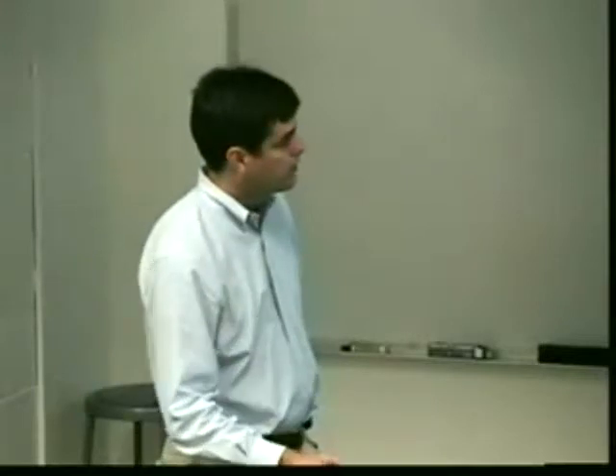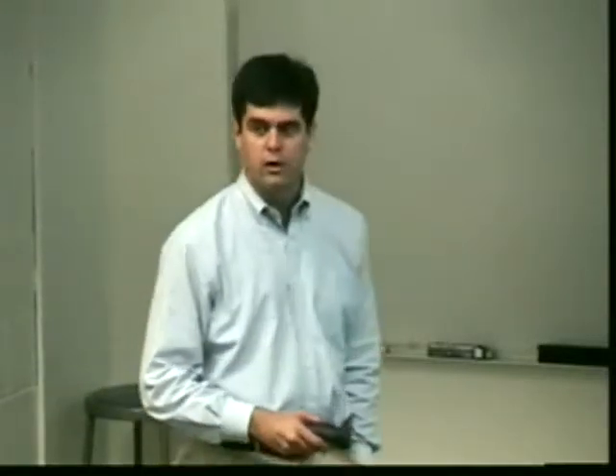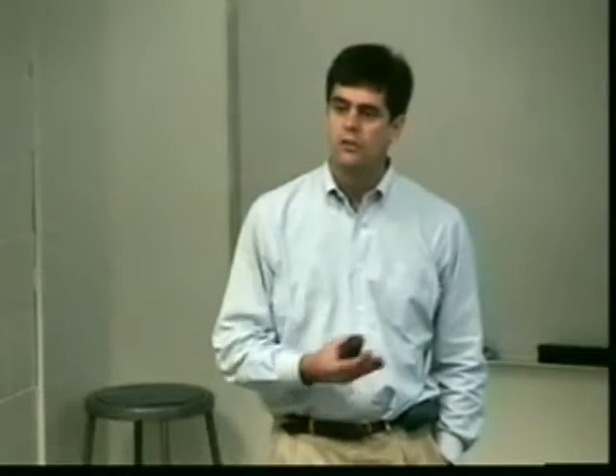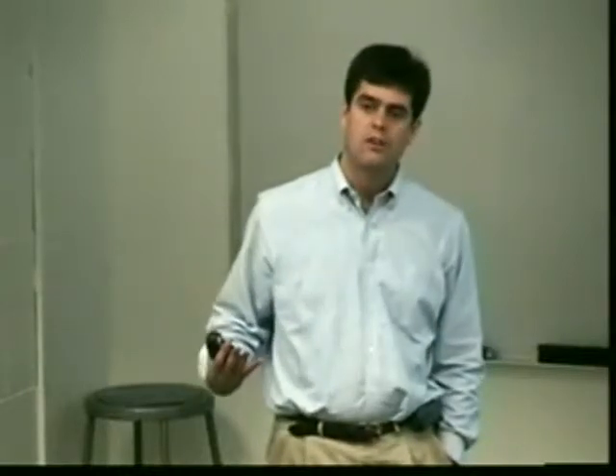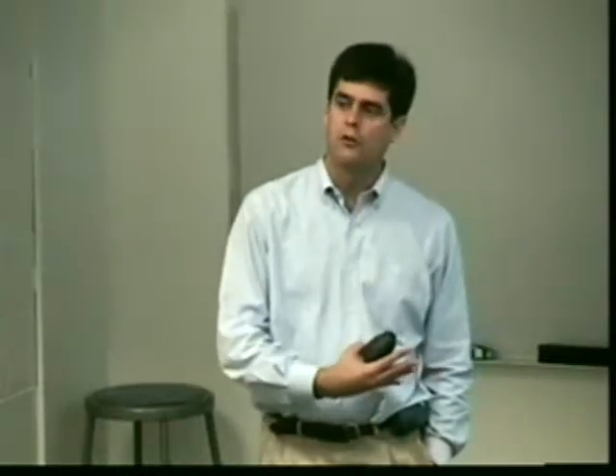need another axis because you have more than one isotope and you're scattering from the nucleus. So, for example, for hydrogen, you've got hydrogen and deuterium. Tritium isn't shown, but in any case, they're different. And similarly, you have different isotopes of the other elements as well. But by and large, as you move down the periodic table, they're all roughly the same size. And also, the cross-section is not correlated with where you are in the periodic table. So you don't have this systematic variation that correlates with chemical properties and so forth.